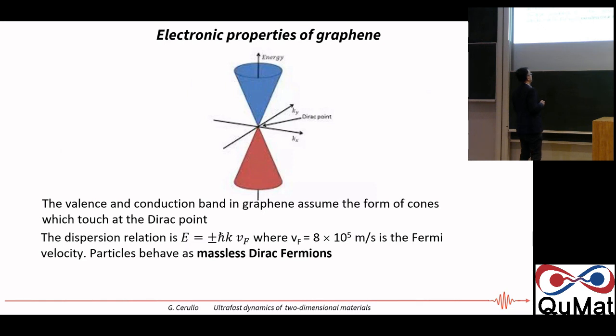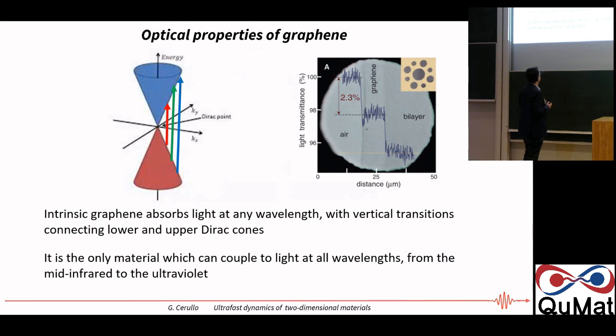Now, the other remarkable property of graphene is that it interacts with light at any wavelength. If you make a vertical transition between valence and conduction band, you can absorb light in completely undoped graphene at any color, from the mid-infrared to the ultraviolet. So it is the only material which couples to light at every wavelength. And this is remarkable for many applications, like photodetectors. You can, in principle, make photodetectors with really broad bandwidth. Now, graphene has a lot of properties, but still it's a semi-metal that doesn't have a band gap. And it was initially fabricated by just exfoliating a piece of graphite. So it was an extremely simple experiment.